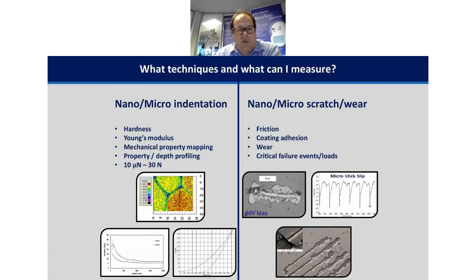We have a whole range of different test techniques. So what are they and what can I do with them? Well, we have instrumented indentation, which is used for measuring hardness and elastic modulus of materials. We can measure mechanical properties at any given point on a surface, across a surface to create a mechanical property map, and as we get further into a material. We can start at the surface and see how these properties change with increasing depth.